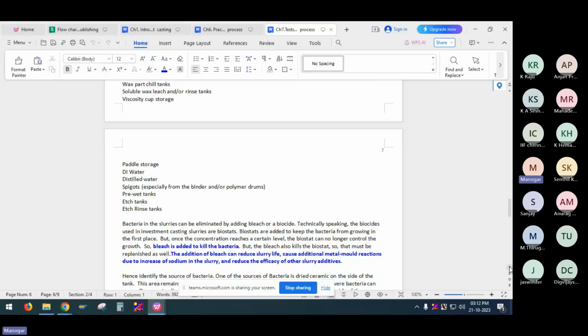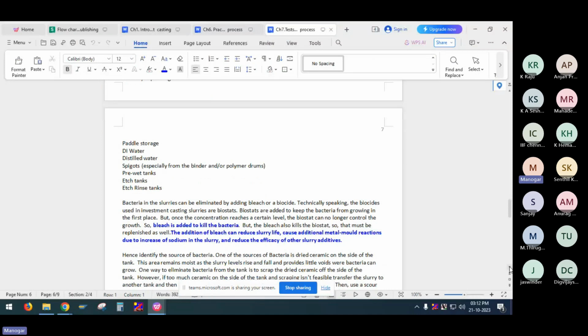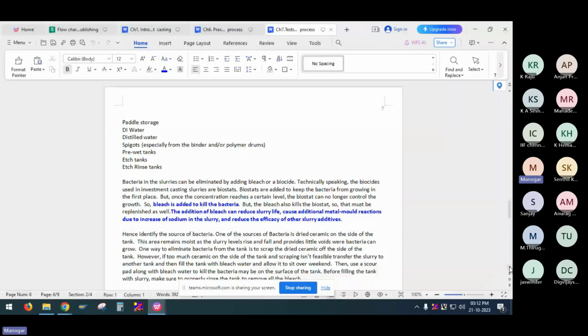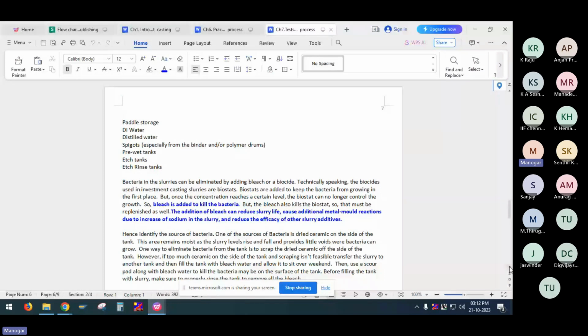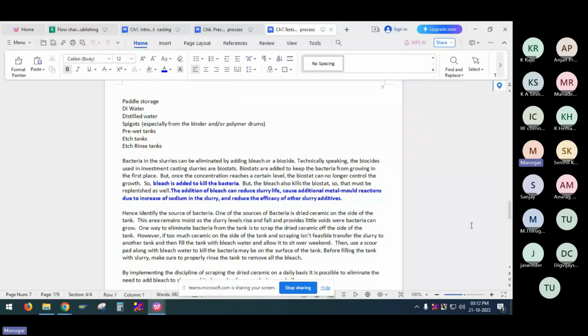But bacteria can be eliminated by bleach or by adding a biocide. Bleach is used to kill the bacteria, but addition of bleach will reduce the slurry life and cause additional metal mold reaction. So it is to be used very rarely, not to be a regular practice. And it also reduces the efficiency of the other additives. So you should control the use of bleach to control the bacteria. It is better to deal directly with the source of bacteria and control it instead of going for biocide or bleach.